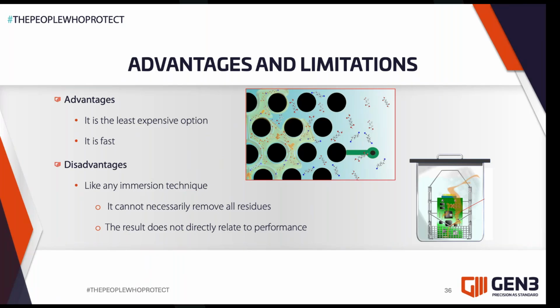That metric comes from the SIR process qualification. Then we can take that knowledge to build up a library value for particular boards, which gives us a pass-fail. So now we have a tool that works in a short period of time and gives us a go, no-go value or control limits which we've established by an SIR investigation. The advantage of the technique is that it's fast, it's repeatable, 15 minutes, and its repeatability has been proven in a study by Robert Bosch, where they achieved 6 Sigma verification of their processes using this approach, and a machine provided by GEN3.